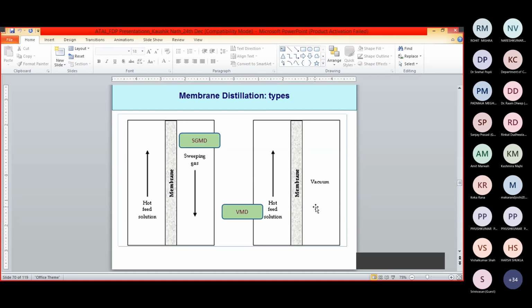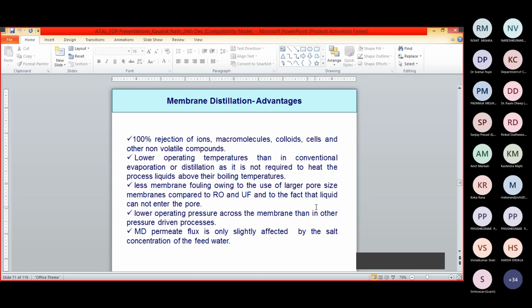permeated vapor. Okay, so advantages of membrane distillation: 100% rejection of ions, macromolecules, colloids, cells, and other non-volatile compounds; lower operating temperature than in conventional evaporation or distillation, as it is not required to heat the processed liquids above their boiling temperature; less membrane fouling owing to the use of larger pore size membranes compared to RO and UF; low operating pressure across the membrane; and membrane distillation permeate flux is only slightly affected by the salt concentration, unlike other membrane processes.